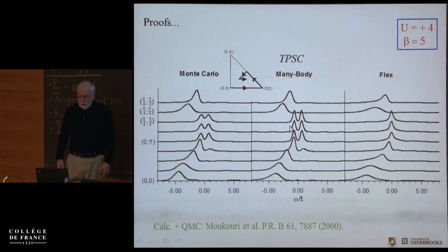So what is the benchmark? Okay, this is the Monte Carlo calculation at a given filling for beta equals 5, U equals 4, and for, I think, an 8x8 system. So you are moving like this in the Brillouin zone. And this is the single particle spectral weight, what you would measure by ARPES. And this bump here is for this wave vector at 0. And then you move for different wave vectors. Eventually, you reach the antiferromagnetic zone boundary. You see a pseudogap opening up. And then if you go far, then the peak just broadens. And you see that the agreement is quite detailed.